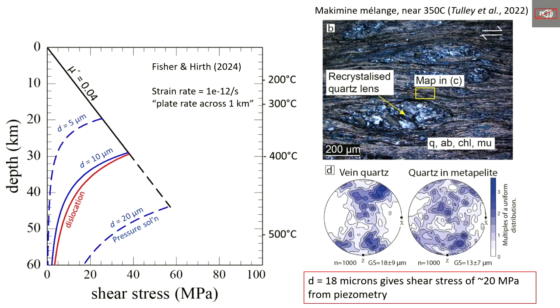So in the Makimine mélange at temperatures near 350, which is the condition of where we started from, you see something cool. You see boudinaged quartz veins with microstructures that are indicative of dislocation creep. And they have the pole figures indicative of this boundary region between the two flow laws we talked about before. And when you look at the quartz in the metapelite, you don't see that fabric. It's maybe a little teeny bit of one, but not really. And it's clear that the pelite is deforming much faster.